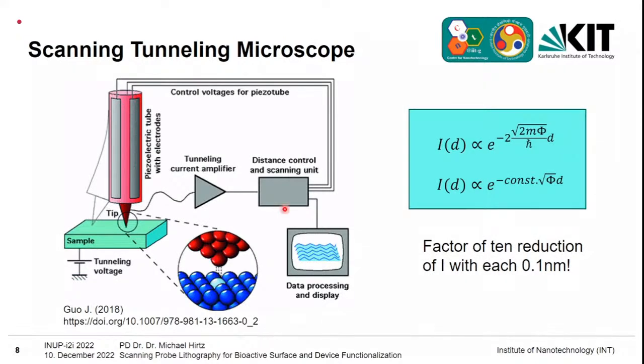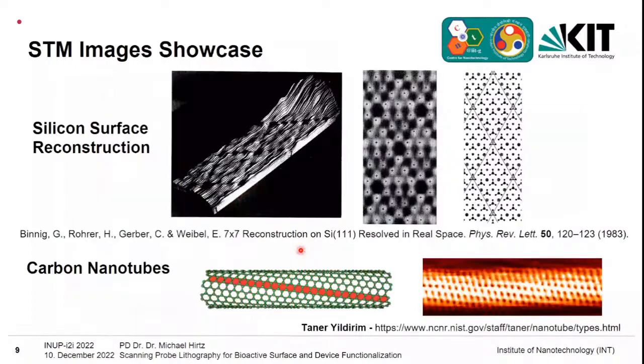And the scanning tunneling microscope exploits this by taking the tip, scanning it over the surface, and monitoring the current. This means that line by line, you can come up with images of the surface by means of the current density. You can see here one of the very first things that came out of a scanning tunneling microscope. That's the surface reconstruction of silicon 111. They could finally reveal that you have this 7x7 surface lattice cell, let's say, for the reconstruction. Nowadays it has become very much more advanced, so the resolution and everything got even better, the stability got better, and you can even do images like this of carbon nanotubes.